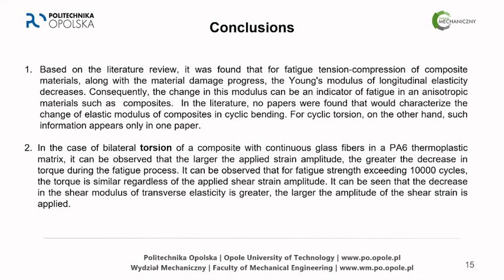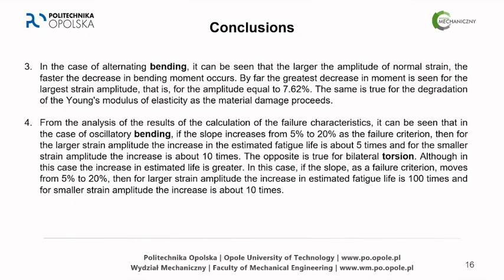However, for this material, we found out that no matter what the strain amplitude was, at the level of 10,000 cycles, we obtained actually almost the same torque. And in the case of bending, we found that when the strain was smaller, then it decreased just a little bit. However, when the strain amplitude was bigger, it decreased actually rapidly. And the last conclusion is that it can be seen that during bending, if the slope increases from 5% to 20%, which was assumed as a failure criterion, then for the larger strain amplitude, the increase is about 5 times, and for the smaller amplitude, it was about 10 times.